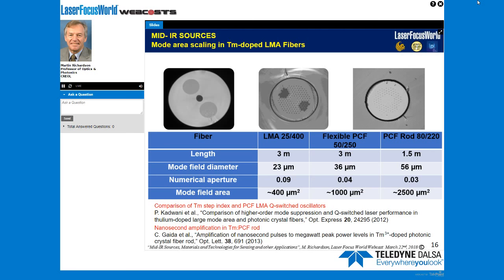architecture, shown in the other two photographs. In the middle case, photonic crystal fibers, where the average refractive index of the cladding relative to the core can be changed by, in essence, the inclusion of a large number of vacancies or holes in the fiber itself. You can see the structures of these fibers. They go to fairly large core sizes, and for high power lasers, where optical damage or the power loading capabilities are a factor, as well as still maintaining single mode propagation, the actual sizes of the fibers become extremely important.